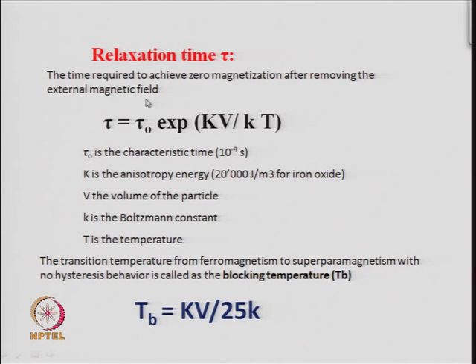So, you apply a field and then remove the field, how much time will the moment require to become 0 again, because in the absence of the magnetic field any paramagnet, and hence a super paramagnet, should also have 0 magnetization, but it will take some time to achieve that. That is called the relaxation time tau, and that is given by this expression: tau equals tau naught exponential of capital K multiplied by V by small k T.